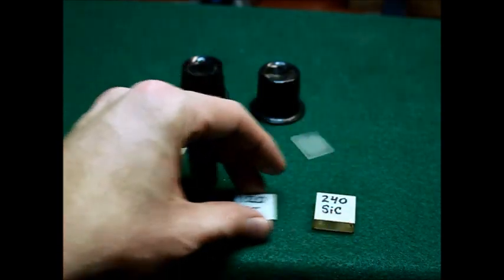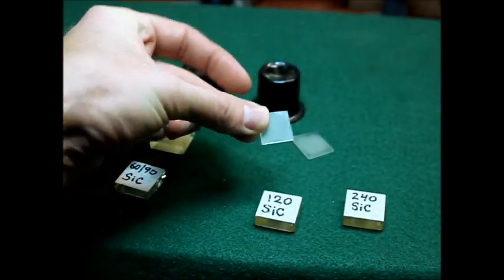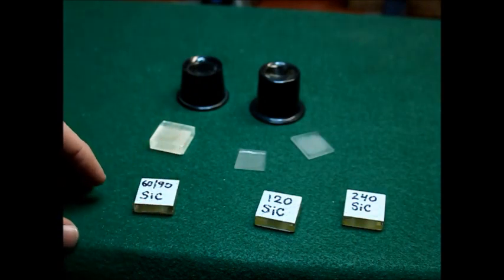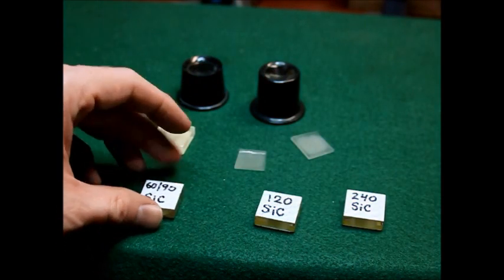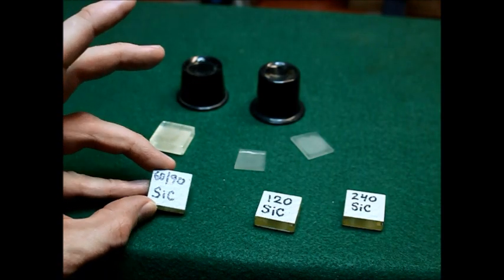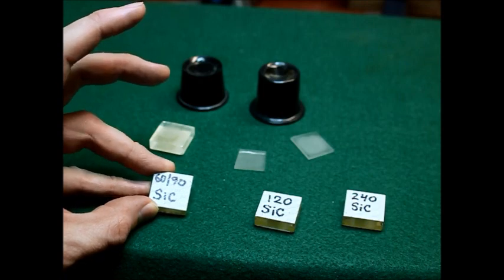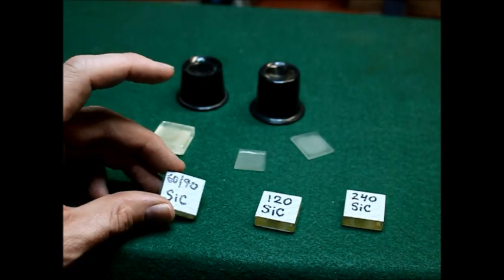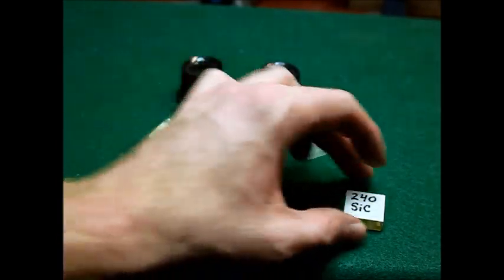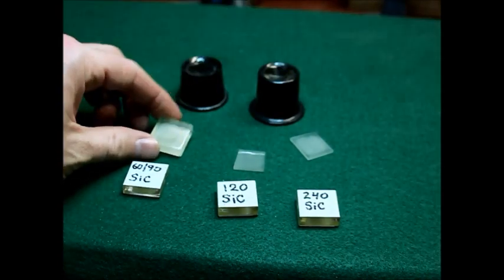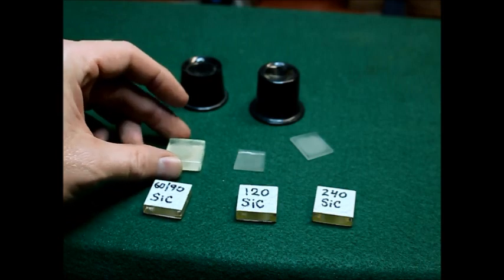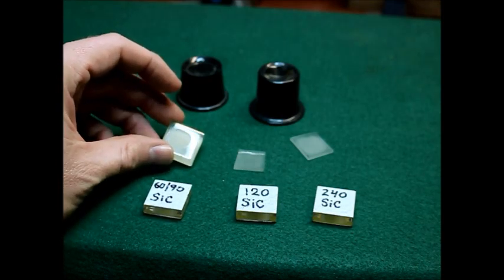And I've labeled a couple of them and I've even used little pieces of glass like this for some of them. But it comes in really handy when you don't know what you're really looking at - you can go back and check your standard and make sure what you're looking at really is a pit and not just something else. Now I've labeled on this one 60-90, that's when I was hogging it out, 120 silicon carbide, 240 and higher. But this is just a suggestion, it's not necessary, but it is very handy to have something like this while you are progressing.